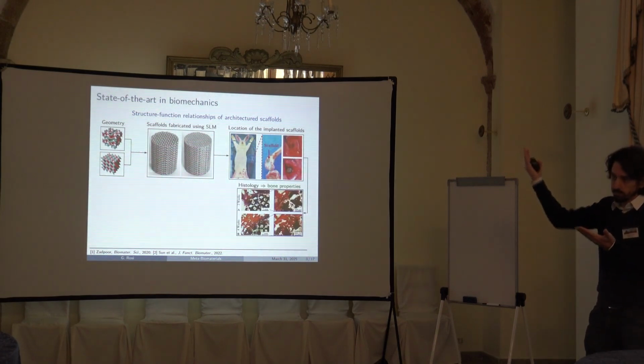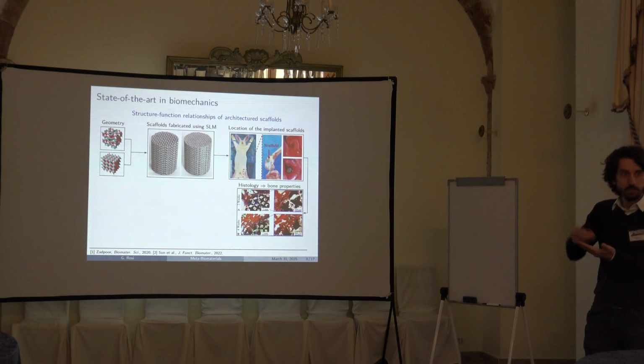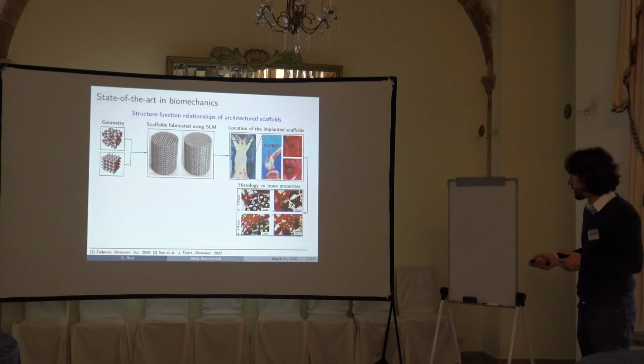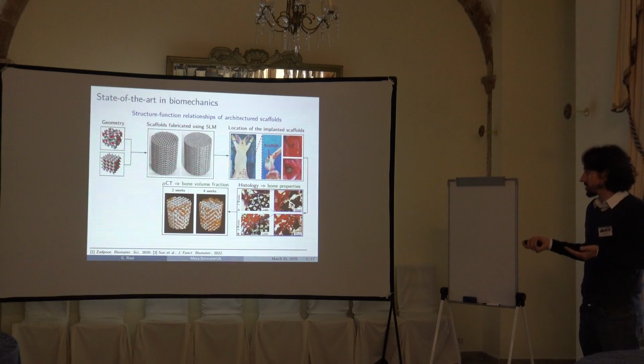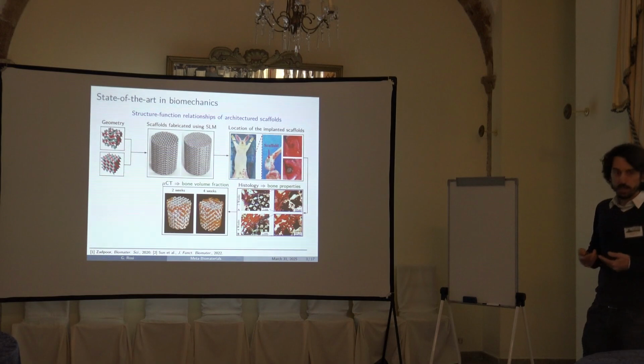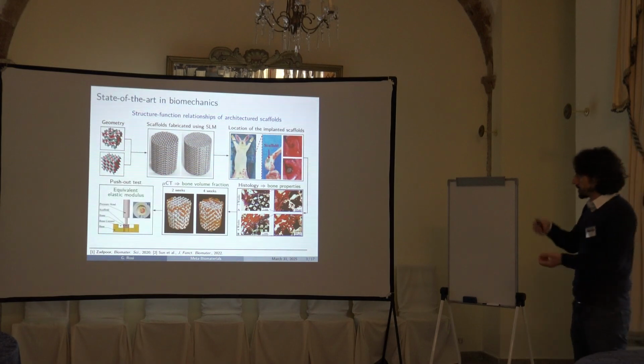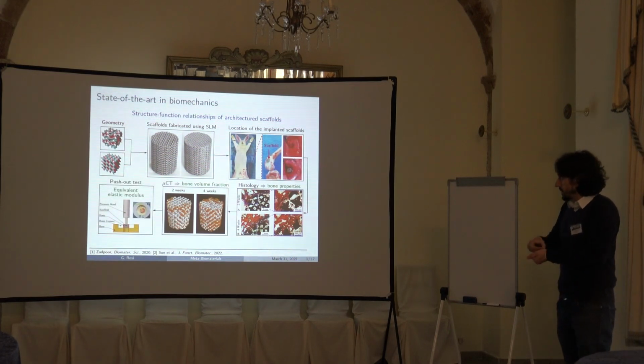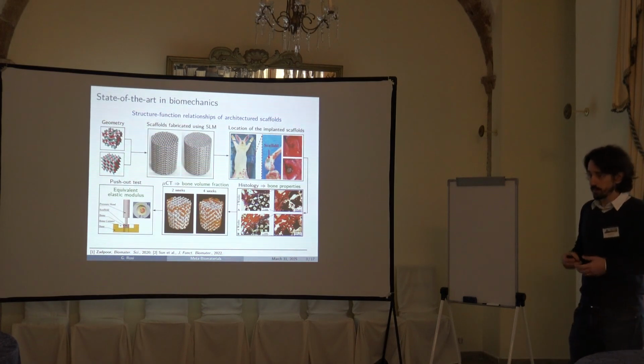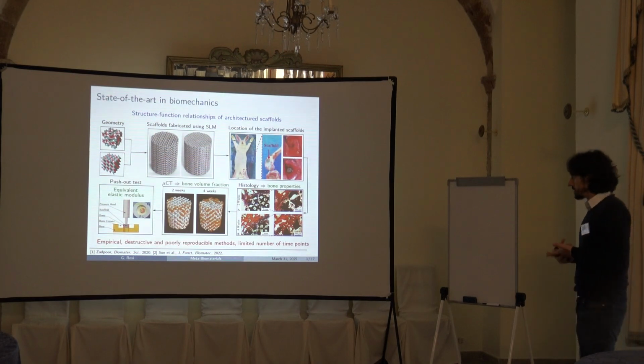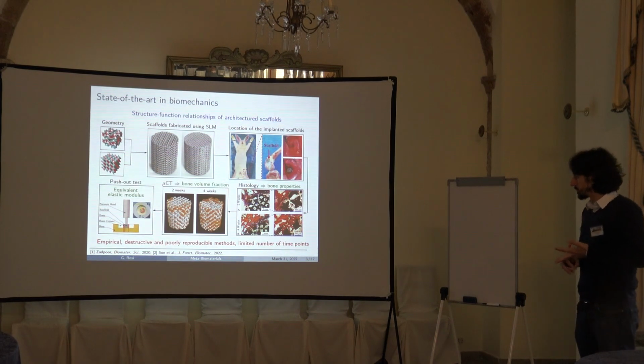You take the implant, you slice it, you put chemicals in order to see where the cells are. You do micro CT. That cannot be done in vivo, so you have to harvest the implant and you can see where the bone is formed and so on. And in order to assess the mechanical properties, you need some kind of pressure test or pull-out, push-out test on the implant. The characteristic of these tests is that they are almost empirical, they are destructive and poorly reproducible.